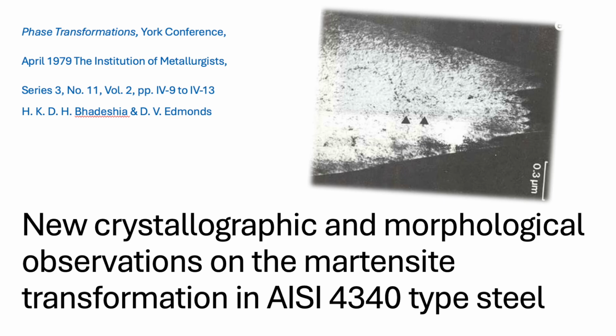Okay, so what do the nickel and molybdenum do specifically in this context? Well, nickel is crucial because it significantly lowers the temperature where martensite starts to form, the Ms temperature. So it shifts the whole transformation window downward. Exactly. It happens over a different, lower temperature range. And molybdenum primarily boosts hardenability, making sure the transformation happens effectively even with slower cooling rates than, say, pure water quenching. So this specific chemical cocktail is designed to give us a quenched structure that's naturally a mix of both lath and plate martensite. That's the result, yes.